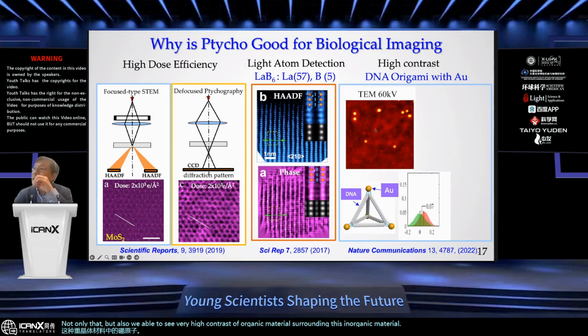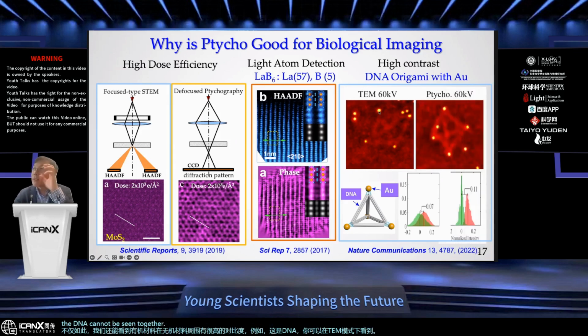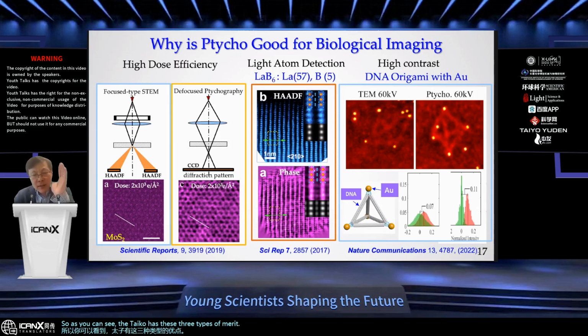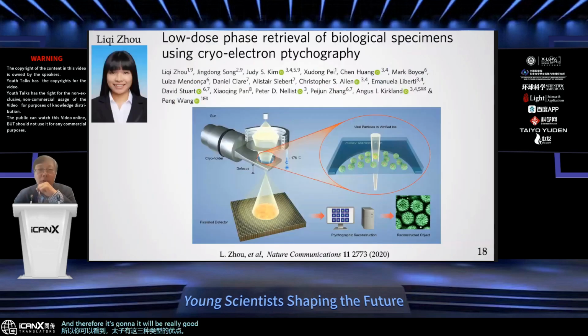For example, this DNA: as you can see in the TEM mode, the DNA cannot be seen together with the gold particle. But if you change to ptychography, the DNA strand can be clearly observed together with the gold balls. So as you can see, ptychography has these three types of merit or advantage, and therefore it will be really good for biological imaging.